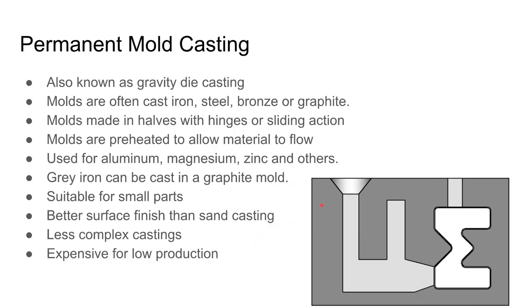The heated metal is then poured into the mold. The goal is to fill the cavity, allow the part itself to solidify, and have the sprue and runner system solidify such that shrinkage happens outside the part. There's a vent at the top, you pour in and fill from the bottom, and there's an internal riser. Soon after the part solidifies, you want to remove it to avoid hot tears.